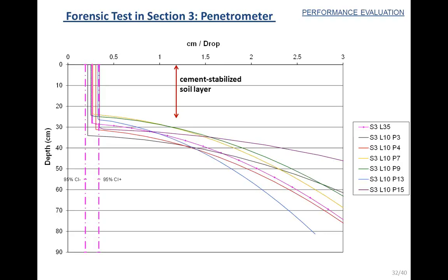So one more thing that we did when we did the forensic testing in section number 3 is that we conducted penetrometer testing. So here you can see the depth, in centimeters. This could be the depth of the cement-stabilized soil, which is 25 centimeters. This 0 corresponds to the bottom of the asphalt layer, right, the top of the cement-stabilized layer. And here you have depth, and in the x-axis you can see the penetration, which is in centimeters per drop.